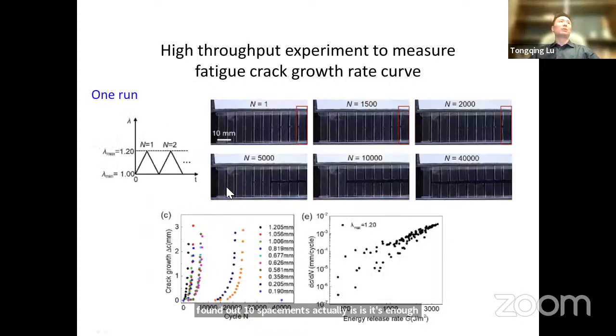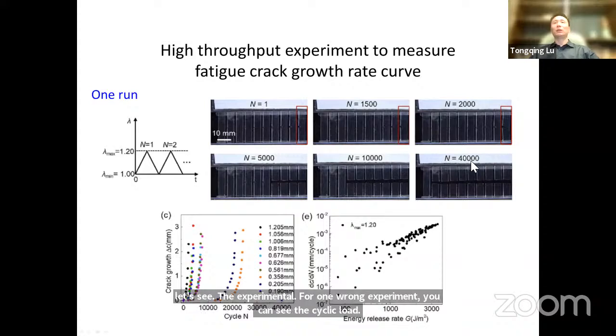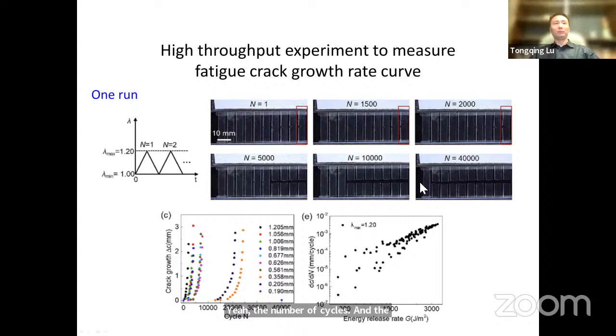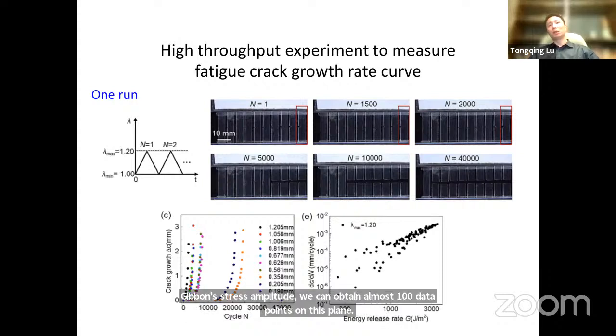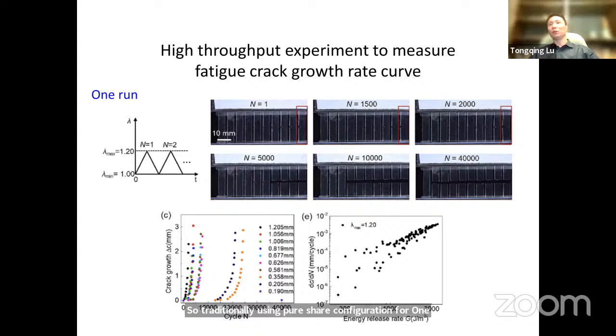For one run of experiment, you can see the cyclic load, the number of cycles, and the specimens rupture one by one. We record the crack growth for each specimen as a function of the number of cycles, and we get this G-DC/DN curve. Note that with just one run of experiment with a given stretch amplitude, we can obtain almost 100 data points on this plane. Traditionally, using the pure shear configuration, for one run of experiment we can only get 1 data point on this plane. It's very efficient.